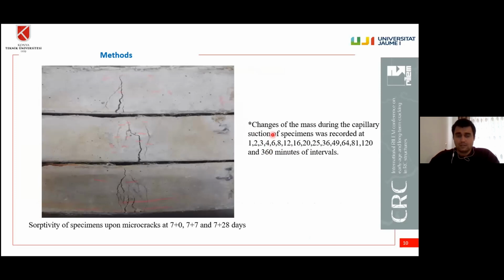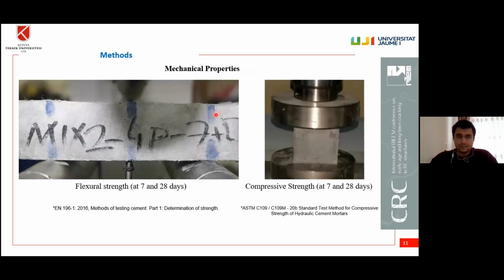For the sorptivity test, we tested on the first day, I mean, when the preloading was introduced, and after 7 days of the first preloading, and then after 28 days. The sorptivity was evaluated in terms of the change of mass during capillary suction. We used time intervals from 1 minute to 360 minutes, and we used the square root of these intervals to see the overall behavior. Apart from the preloaded specimens, we separately evaluated the mechanical properties of the specimens. As you see, we used flexural strength tests and compressive strength tests according to relevant standards.